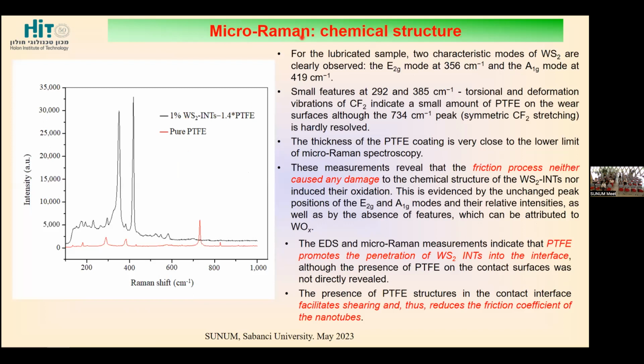The chemical structure was again proved by micro Raman. We detected these two peaks, which are very characteristic of WS2 nanotubes. According to their position and relative height, we know that the crystal structure of the nanotubes was not compromised. We also have very little Teflon, right on the limit of micro Raman detection, because micro Raman detection is about 1 micron, and our Teflon layers were much thinner than 1 micron. But we proved that there is no oxidation and no destruction of the structure, and the presence of Teflon structures in the contact interface results in shearing and is responsible for the reduction of the friction coefficient.